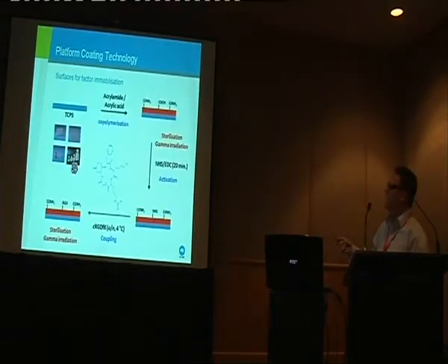At this stage, if we like, we then do a simple activation step, very widely used chemistry, EDC and NHS activation. We get an NHS surface, we immobilise the peptide on overnight, and then we get an RGD-containing surface, which we can also gamma sterilise at that point.